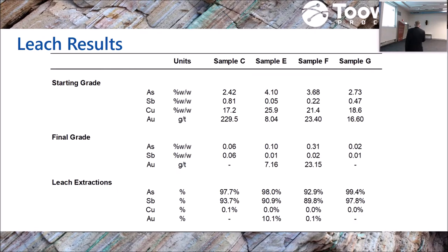Just a few examples to highlight some of these concentrates we've treated: 2 to 4% arsenic, up to 0.8% antimony, coming out at very low levels. Typically less than 0.2 and often less than 0.1% arsenic. And that's our aim. From a process point of view, we want to remove almost all the arsenic and antimony so that we can treat the smallest amount of concentrate to reduce the cost of the process.